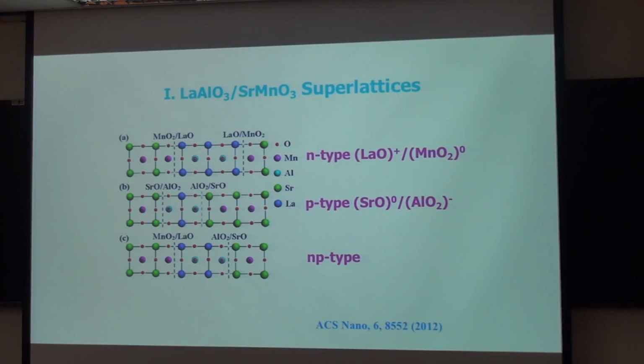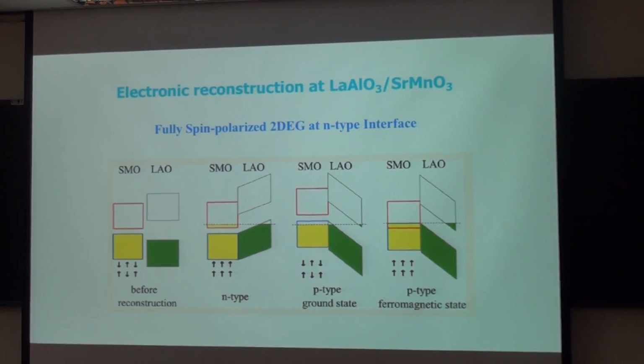or others? So we construct 3 types of superlattice, which is called N-type superlattice, containing merely N-type heterointerface. We also construct a P-type superlattice, as well as an NP-type superlattice, which consists of both N-type and P-type heterointerface. The result is here. We can find in the N-type superlattice, the system transformed from the previously antiferromagnetic order to the ferromagnetic one. And for the P-type, the system is still the antiferromagnetic coupling.